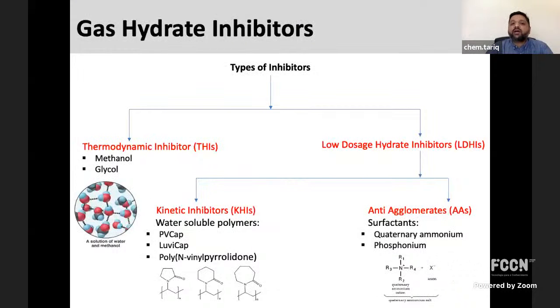These chemical additives are known as gas hydrate inhibitors, and there are different types. The most classical ones are the thermodynamic inhibitors, which are generally methanol or glycol. They do preferential hydrogen bonding with the available water, so that you don't have enough water available to form the hydrates. The problem with them is that you need to use them in very huge quantity. Barrels of methanol and glycols are needed, and glycol is highly viscous, which causes problems and additional cost of pumping. Also, putting this much in the sea can cause environmental concern.